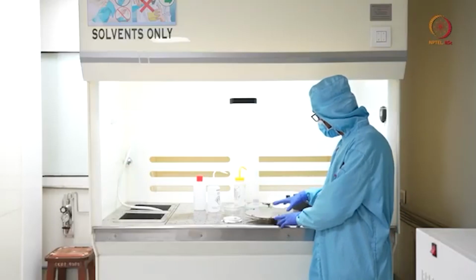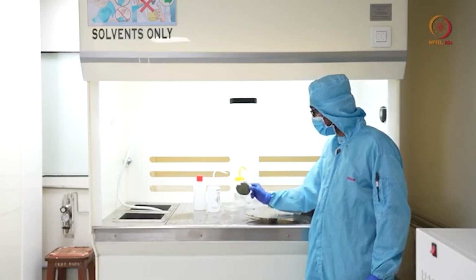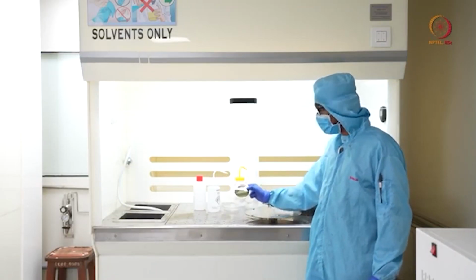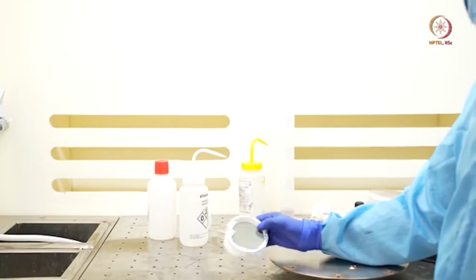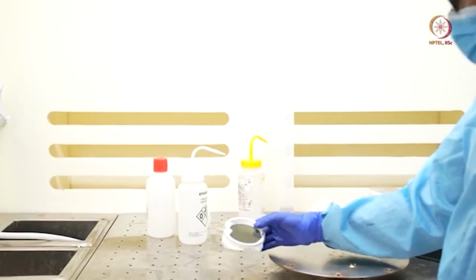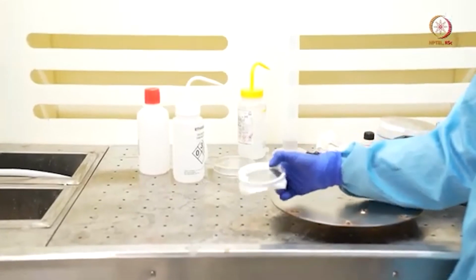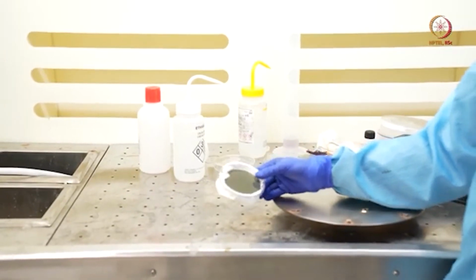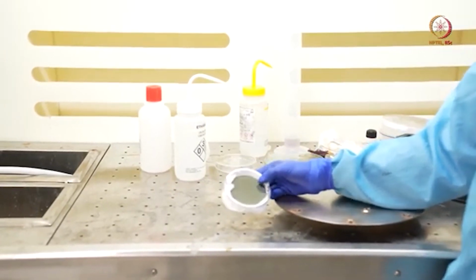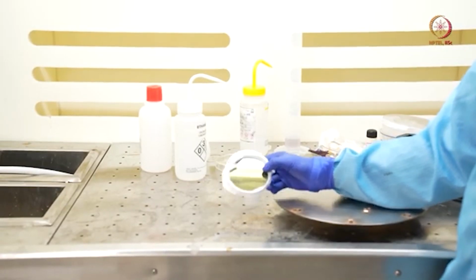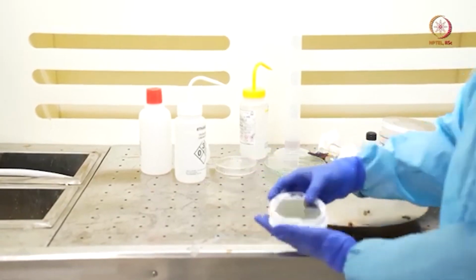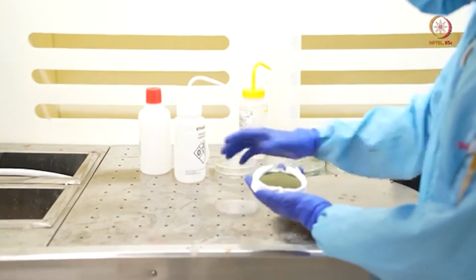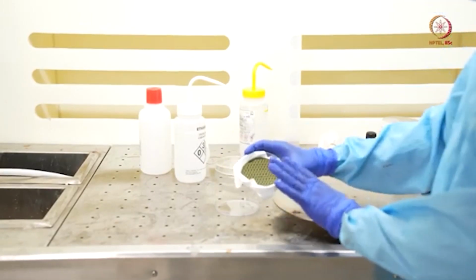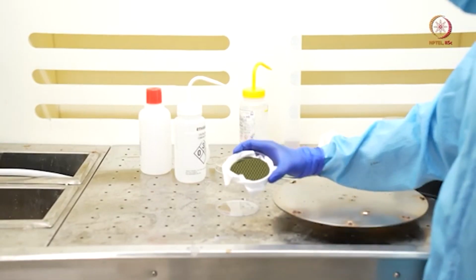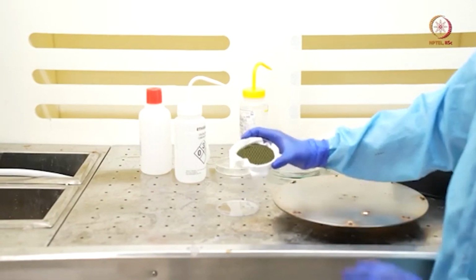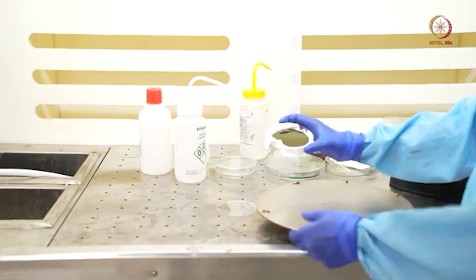So here, as I kept here, you can see that after lithography, the sample is already here. It was in a desiccator overnight after post exposure bake and development, and after development we performed a hard bake for 3 minutes. After that, this is the sample where last day we showed you the patterns as well. It was kind of visible at that time. So we load this sample on this chuck and place it inside.